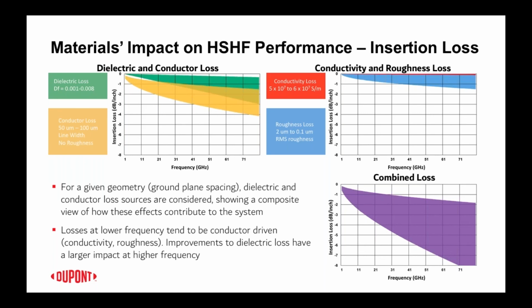In considering how these impact a circuit, it's important to recognize that in this range, it has a fairly linear effect with frequency. And so as frequency goes up, if it's a 5 mil conductor spacing to the ground plane or 2 mil conductor spacing to the ground plane, the dielectric loss is going to be, again, a linear effect with frequency. Conductor loss, on the other hand, is something that's going to scale inversely with the amount of conductor that's there. And the yellow portion of the curve here, where it's overlapping with the dielectric loss, shows how conductor loss is going to vary from 50 to 100 microns line width.